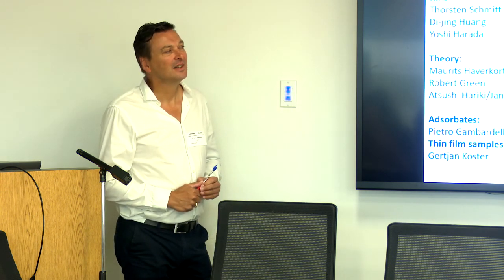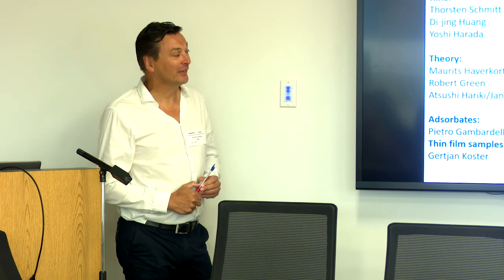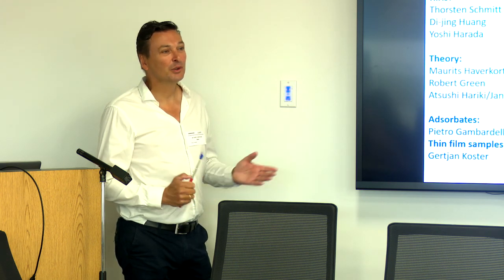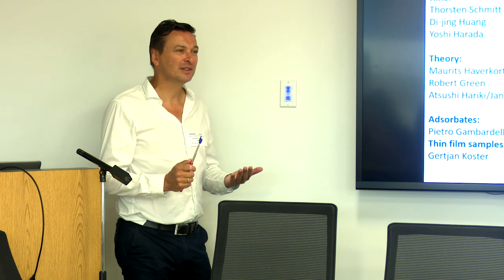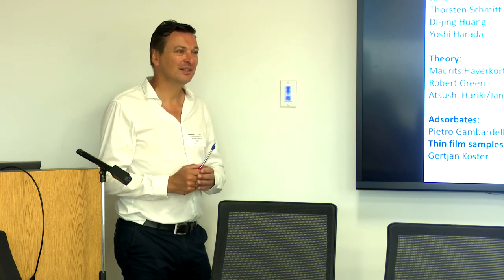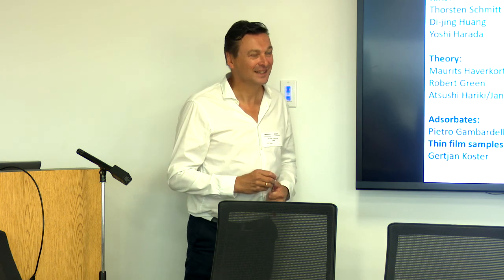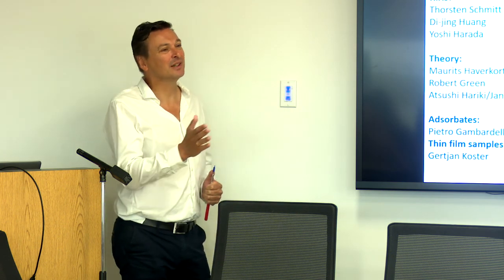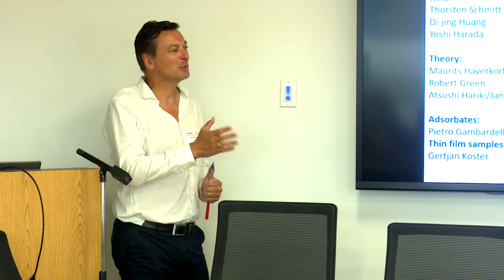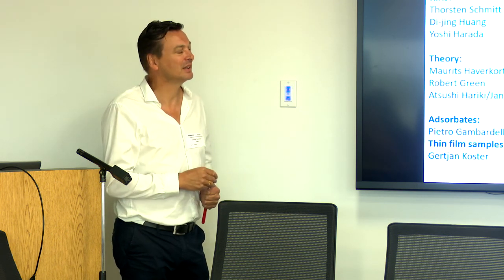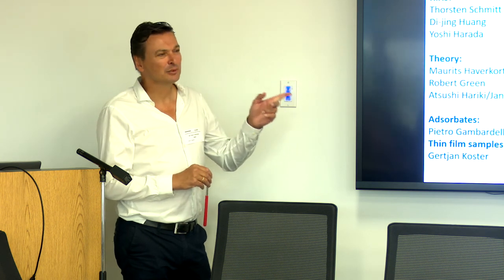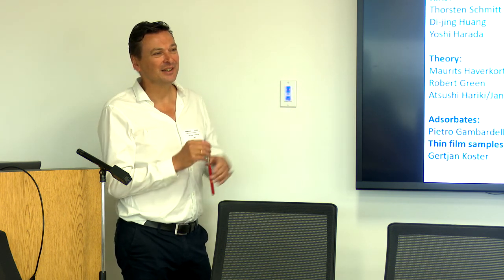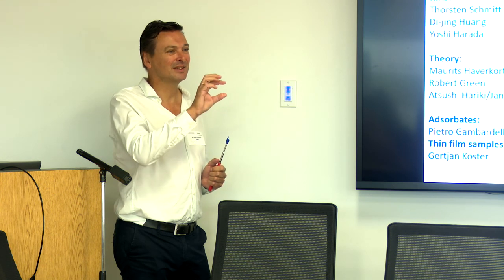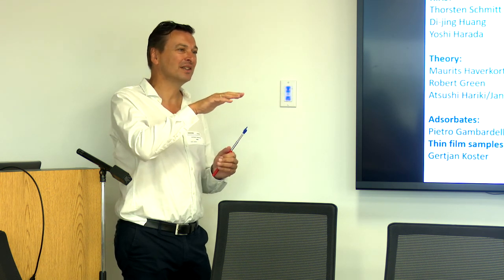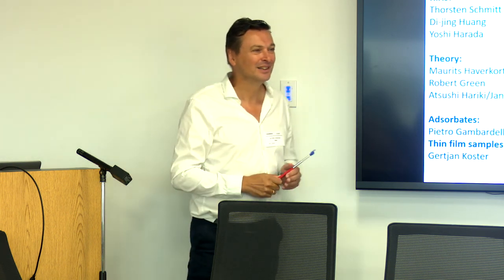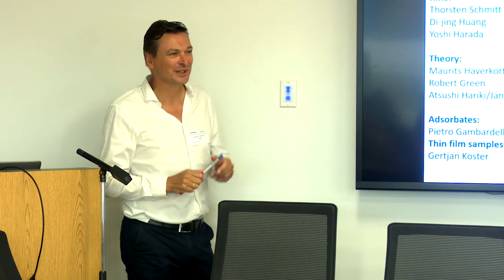Yeah, I think that before, we could not really think about it because we had no experimental, direct measurement wasn't so feasible, in other words. Yeah. So conventional wisdom was convenient, right? Yes. Convenient and maybe also enough, because for X-ray absorption I think it's probably enough to use that rule. And the second thing is ruby is not the normal system. I mean the local site is very low symmetry, and that's the ideal case for this non-conventional ratio to happen.